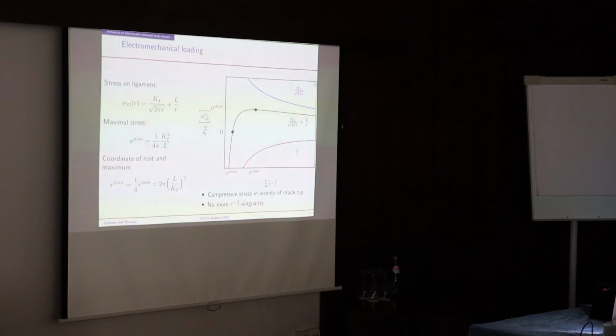Any other question? I'd maybe like to add a comment. So I think the most challenging thing is to interpret the black curve here, because if you have compressive stress at the crack tip, that means that the crack will never grow, which doesn't happen in an experiment. So obviously there's something wrong. So one thing is maybe, as Alexander said, the continuum mechanics hypothesis is violated, just because it's a very small area, a compressive area on the crack tip. But we still think about how to interpret what we see here in terms of fracture mechanics.